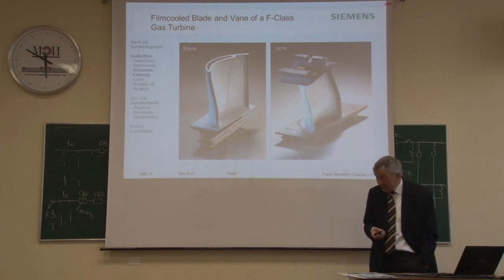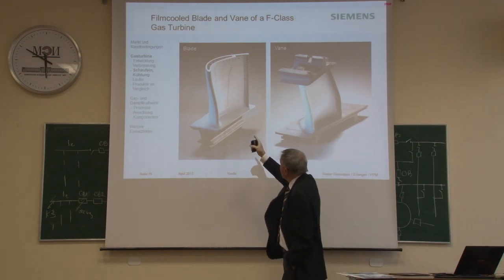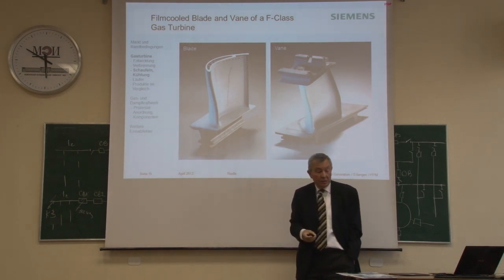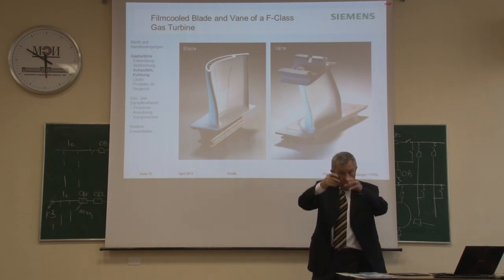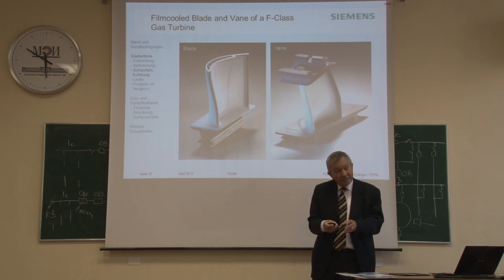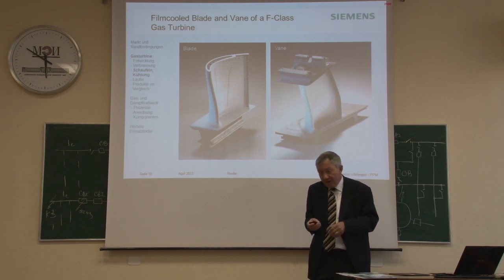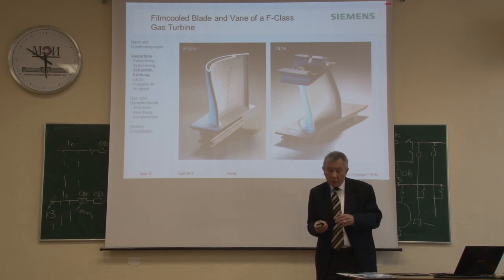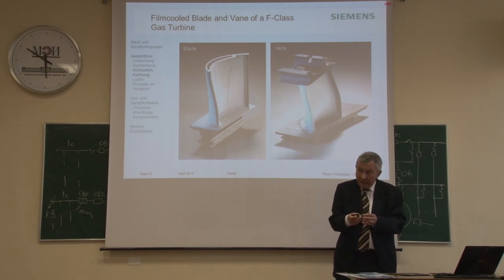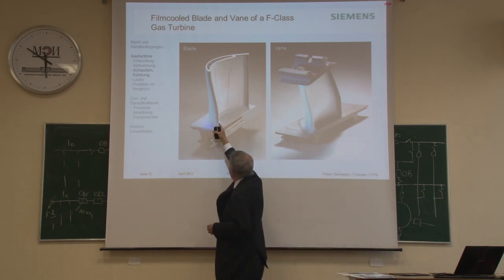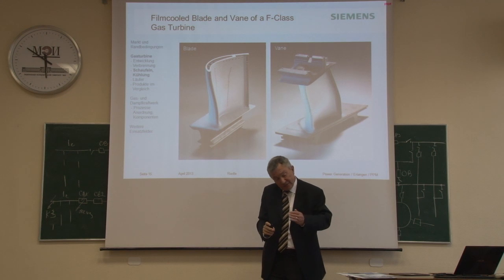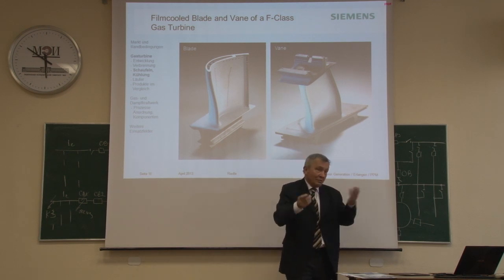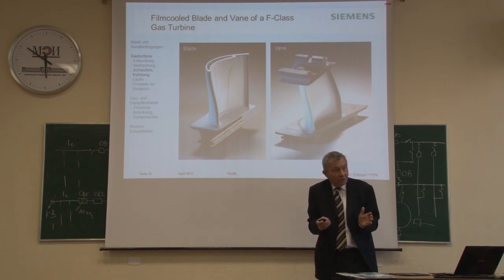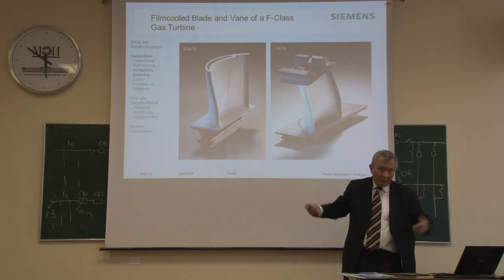Again, a photo out of Professor Buro's book. It's a rotating and a stationary blade. And the interesting thing are those rows of holes. What are they for? Originally, we had cooling only by getting cooler air at the inside of the gas turbine, taking the heat off. But with the intent of raising the gas turbine temperature further, we went to a cooling technology where part of that cool air comes out here, for example, at the nose or close to the nose, and puts itself like a thin layer of cooler 400-degree air